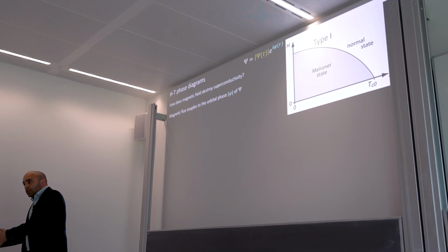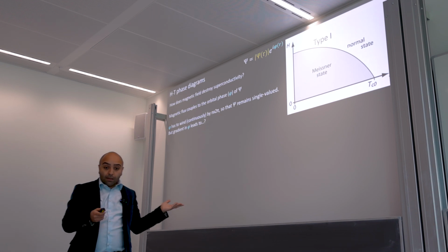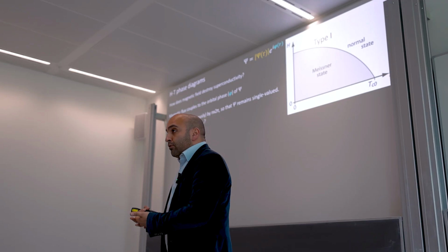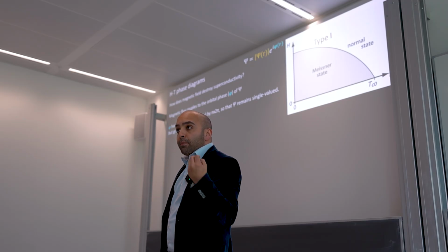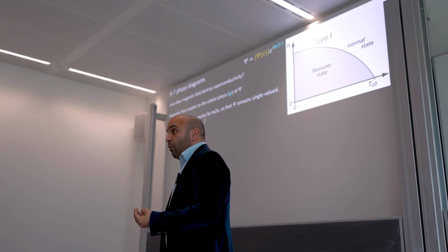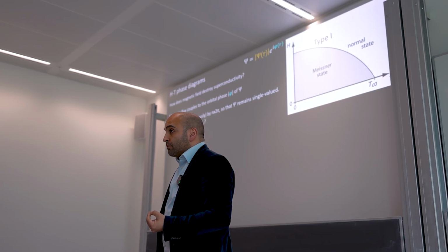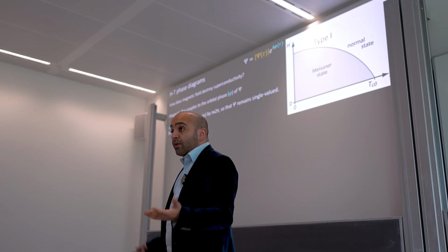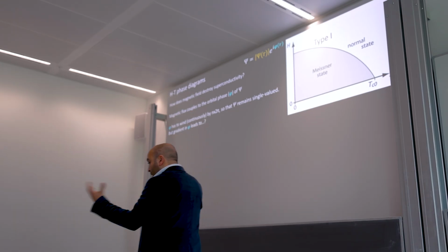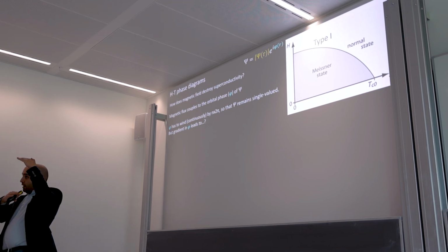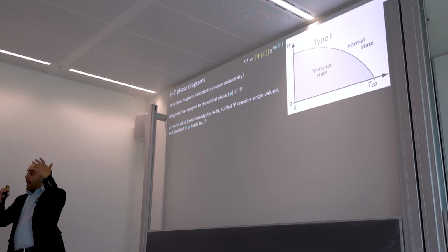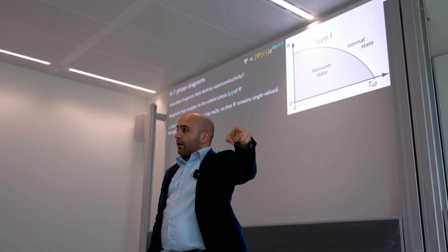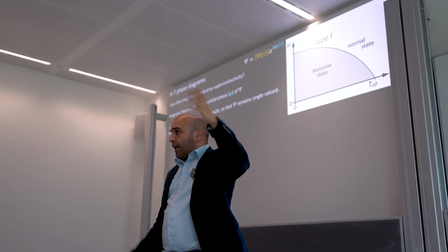And that supercurrent obviously has some energy, kinetic energy. So you generate a supercurrent, sure, it's dissipationless, but it still costs energy. Now, where does that energy come from? It comes from your condensate. Your superconducting condensate, your order parameter, has a certain energy. Your gap has a certain width, and you can quantify it in terms of energy. So this Tc of your superconductor, you can directly convert to energy in electron volt units.